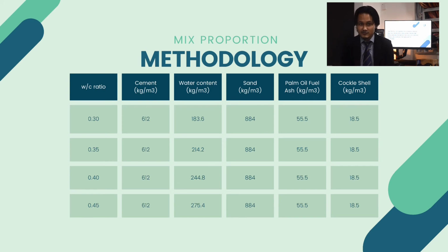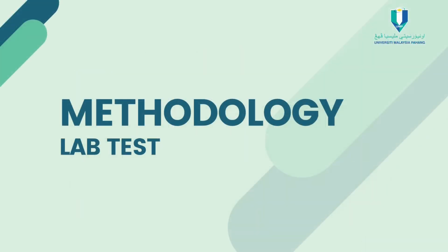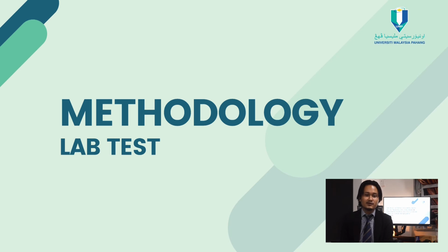This is my methodology of mixed proportion. The water cement ratio is from 0.3 to 0.45, and the cement value is 612, and the water content is 183.6 to 275.4, and the sand is 884 kilogram per meter cube. For POFA, I will use 55.5, and the cockle shell is 18.5 kg per meter cube.